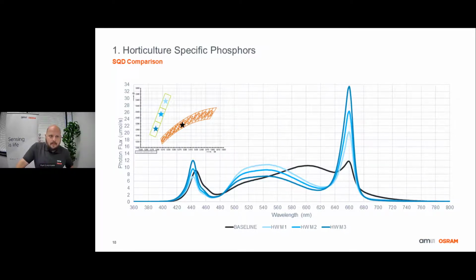Now that we have all four solutions overlaid on each other, you can see that we have fundamentally changed the shape of the spectrum. However, all four of these spectrums still have that same red to blue ratio of 2.5 to 1. The most significant change is happening in the red range, specifically between 600 and 640 nanometers, where a majority of those phosphor converted inefficient red photons that were emitted from that white LED have been replaced with a direct emitting red LED between 650 and 670 nanometers.